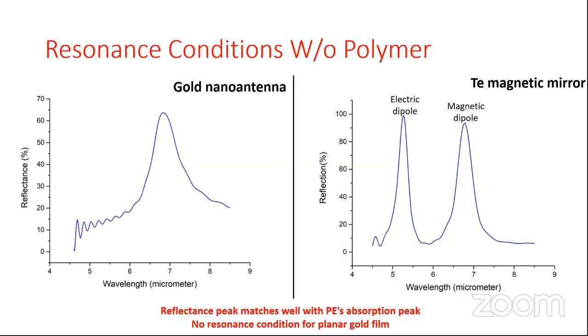And here you could see the gold nano antenna, or plasmonic sensor, and on the right you could see the telluride magnetic mirror. This was shown for the resonance conditions with no polymer coating. So this is just the optical response of those 2 different structures. You could see the reflectance peak of the gold nano antenna corresponds to around 6.8 micrometer, which is also the absorption peak of polyethylene. And on the right, there are two reflection peaks. The left comes from the electric dipole and the right comes from the magnetic dipole. And the magnetic dipole is the one that we're interested in. You could see the reflectance peaks match well with polyethylene's absorption peak. And I haven't shown it, but there's no resonance condition for planar gold film, as could be imagined.